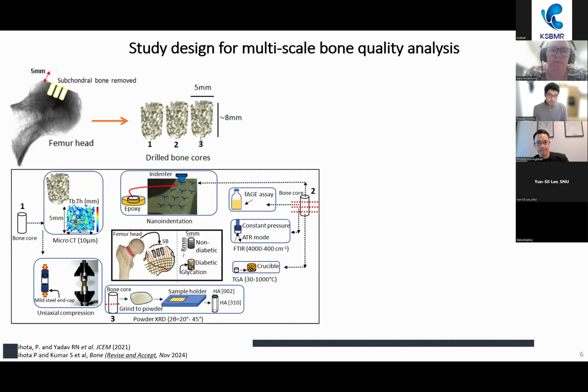So how did we allocate the bone specimens for multi-scale bone quality analysis? Three to four trabecular bone cores were extracted from the femoral head, and one bone core was dedicated to micro CT analysis for measuring microstructure. Then we tested it with a compression test. The second bone core we used for small scale analysis, where we performed the FAGE assay, that is fluorescent advanced glycation end product assay, FTIR in ATR mode for local bone composition, and gravimetric analysis for bulk bone compositional analysis. Then the bone core was embedded, polished, and used for material testing. The third bone core was ground into a fine powder, and then crystal structure and crystal size were studied.